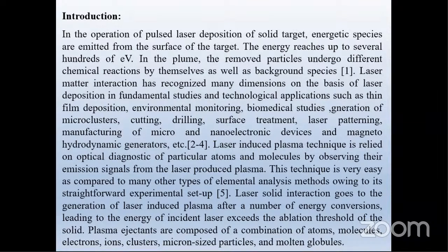Laser-induced plasma technique relies on optical diagnostics of particular atoms and molecules by observing their emission signals from the laser-produced plasma. This technique is very easy compared to many other types of elemental analysis methods owing to its straightforward experimental setup. Laser-solid interaction leads to the generation of laser-induced plasma after a number of energy conversions, when the energy of the incident laser exceeds the ablation threshold of the solid. The plasma ejectants are composed of a combination of atoms, molecules, electrons, ions, clusters, micro-sized particles, and molten globules.